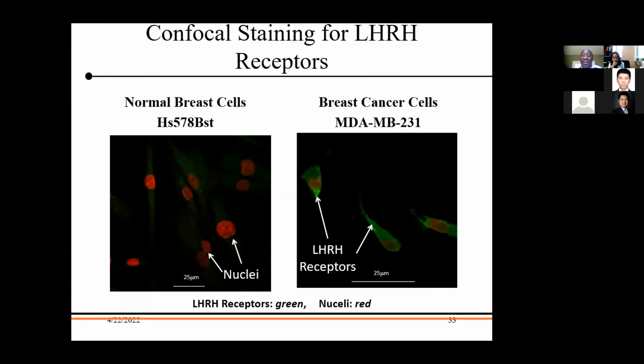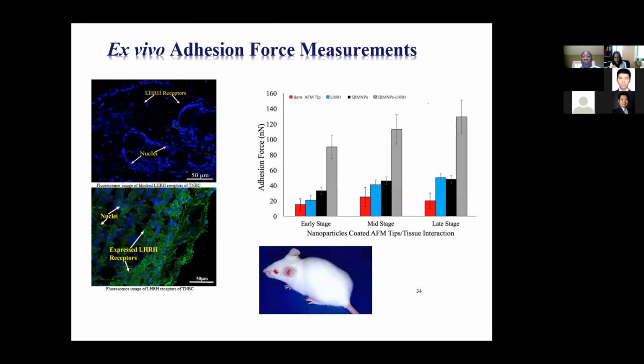The reason it works at the cellular level is because you have overexpressed receptors, which are these LHRH receptors in green. And these receptors are overexpressed by a factor of 4 to 5 or 6 compared to those in normal breast cells. Now, if you look at breast cancer tissues at different stages of development induced in mouse models, what you find again is that the overall adhesion increases with stage. And that increase in the overall adhesion is associated with the overexpression of these LHRH receptors at those later stages